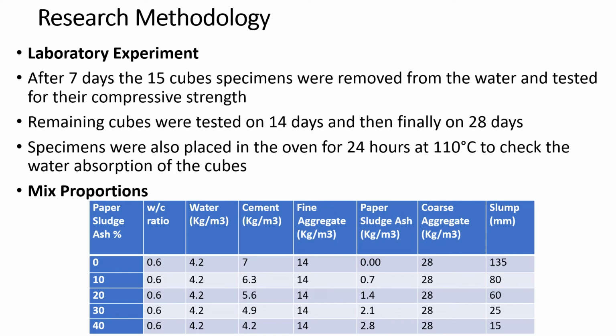15 cubes were tested after 7 days to check its compressive strength. The remaining cubes were tested after 14 and 28 days. For the water absorption test, the samples were kept in the oven for 24 hours at 110 degrees centigrade.